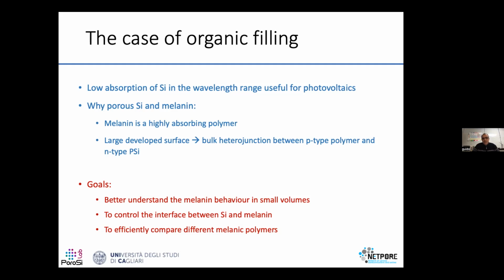Many strategies have been tried to optimize the system, in particular trying to modify the surface of silicon by patterning the surface or using porous silicon as an anti-reflecting layer. But we can do something better, which is we can use polymers, which are P-type mainly, in particular melanin, which is also a highly absorbing polymer, to put inside a porous silicon structure made with N-type silicon. So you will have a bulk heterojunction, that is a large active area made by the PN junction between the polymer and the N-type silicon. And you have to understand how this melanin behaves within these small volumes to control your system.